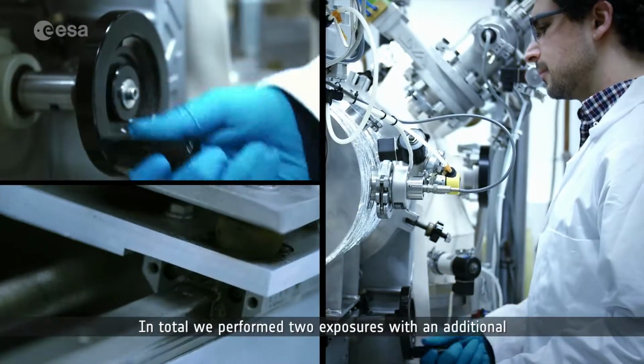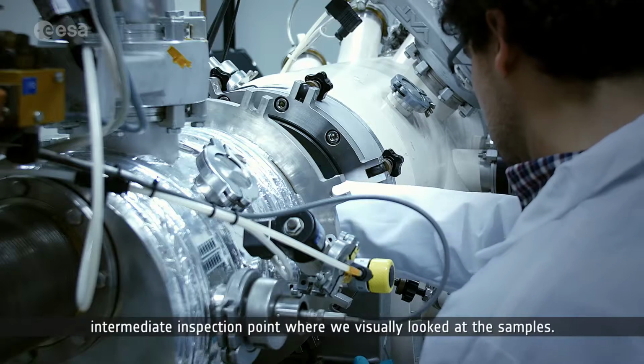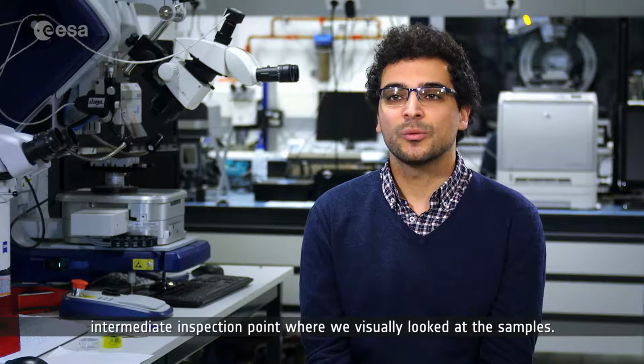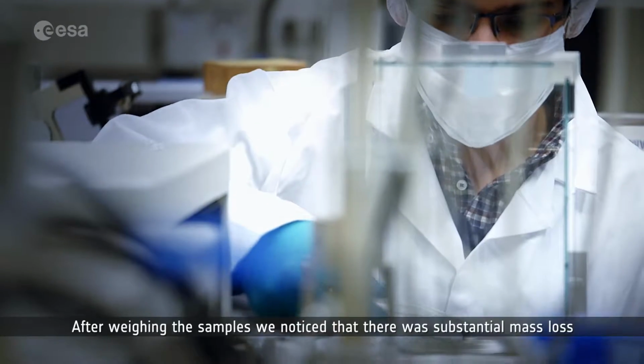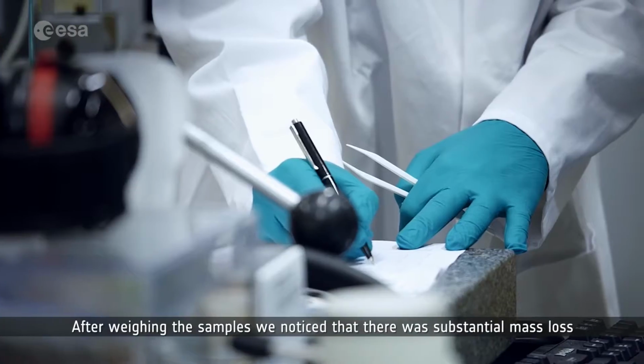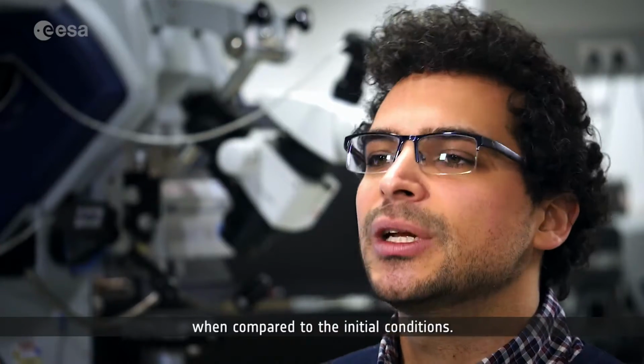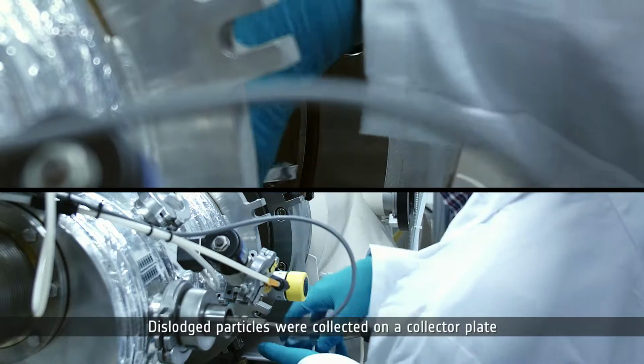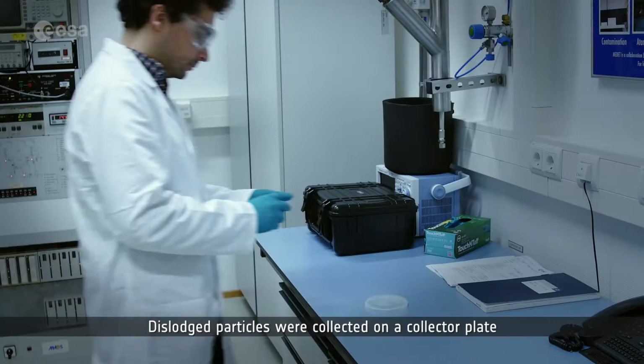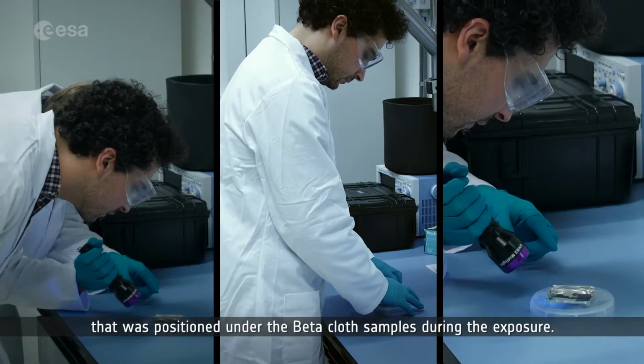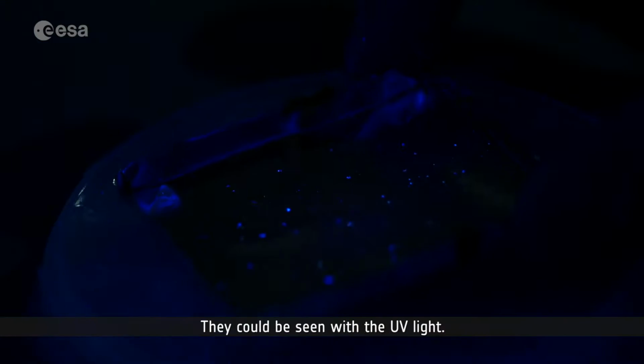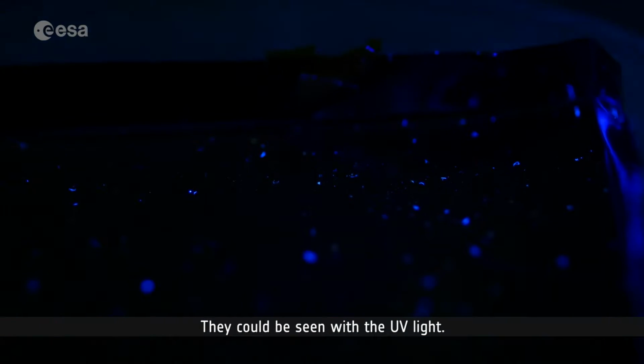In total, we performed 2 exposures with an additional intermediate inspection point where we visually looked at the samples. After weighing the samples, we noticed that there was a substantial mass loss when compared to the initial conditions. These dislodged particles were collected on a collector plate that was positioned under the beta cloth samples during the exposure. They could be seen with the UV light.